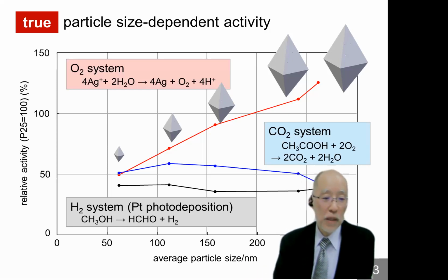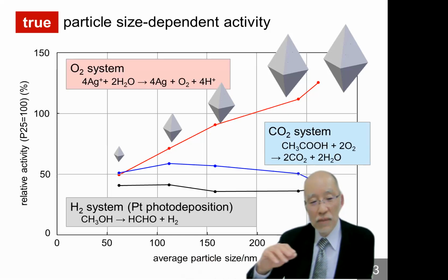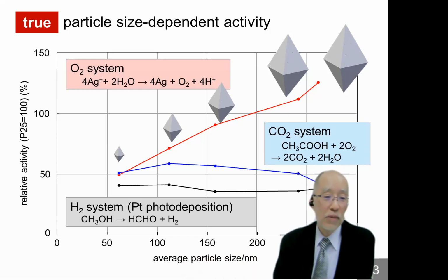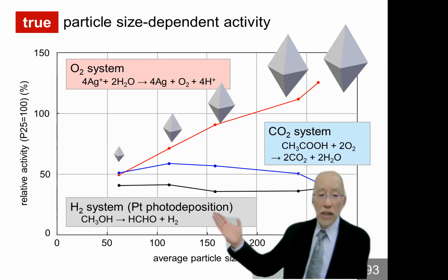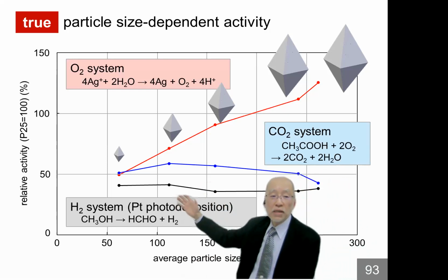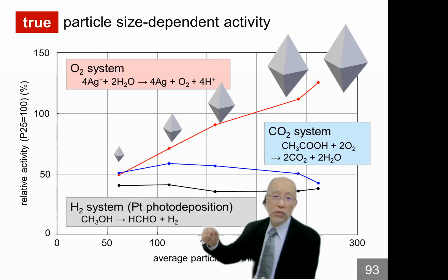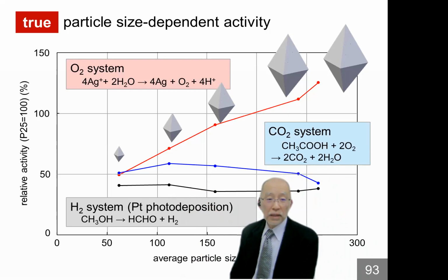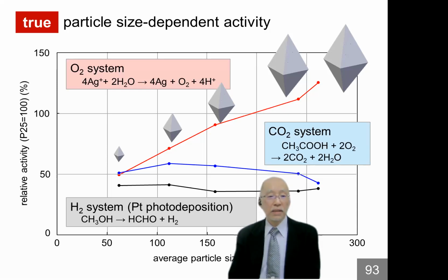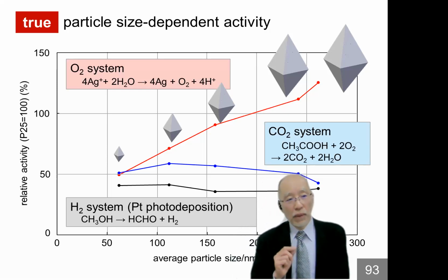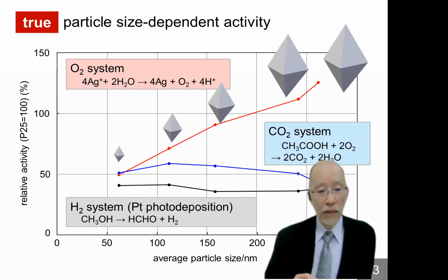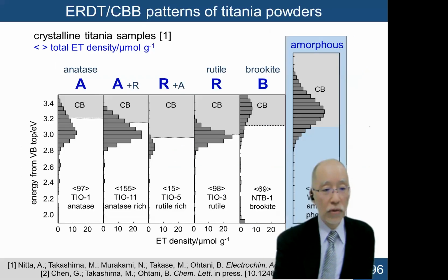Probably for the previous papers, the data, of course, the particle size is different, but the other parameter must be changed accompanying the change in particle size. But in this case, bulk structure and surface structure is the same. Only the size is different. This is true particle size dependence of photocatalytic activity of samples. So probably this is the first results of pure true particle size dependent activity. And that can be supported by ERDT/CBB pattern for purity of surface structure.